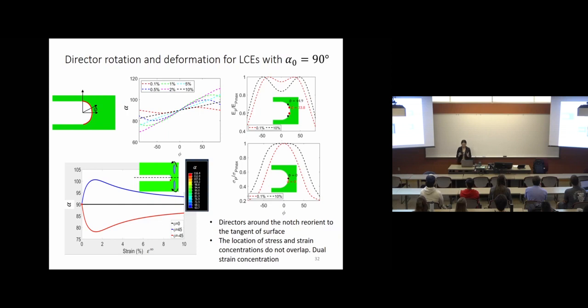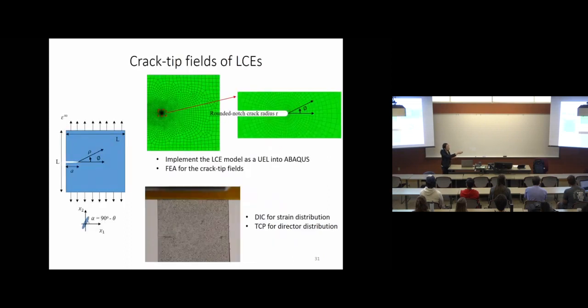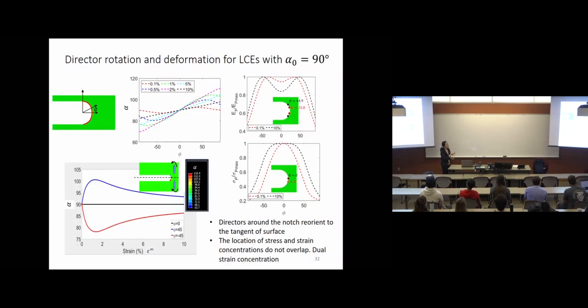First of all, what I'm showing you here is for the case where I'm defining another angle, alpha. Alpha is the complementary angle of theta, which describes the orientation of the director, but now this alpha angle is with respect to the x-axis. When alpha equals 90 degrees, the director is along the stretching direction. Then let's look at the video here. This is describing the director change as a function of strain at three different locations, at 0 degrees, 45 degrees, and negative 45 degrees. Let's look at the result here.